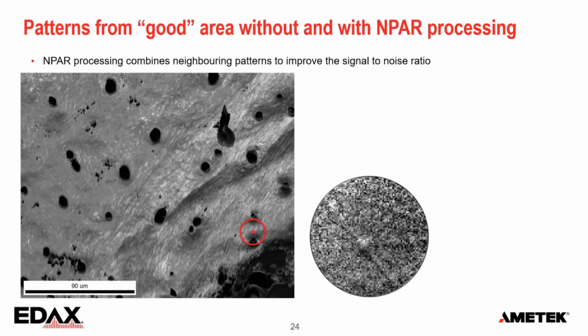Now, this is what brings me back to this averaging. We saw that when you go from very low current and you average 15 times, the pattern quality dramatically improves. And that is something that we can do with the tool we call NPAR, neighbor pattern averaging and reindexing.